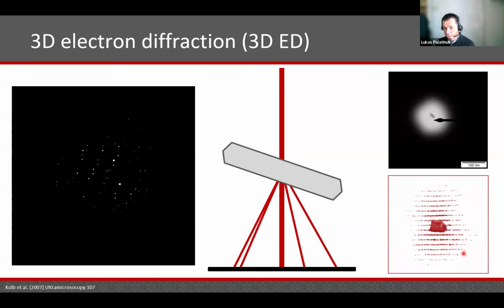There are certain experimental challenges that need to be overcome related to the stability of the crystal. You can imagine that keeping a crystal that is 20 nanometers in size in the beam while rotating plus minus, say, 50 degrees is a challenge. But these are experimental difficulties that have been to a large extent overcome in the past years. So now we can say that a reliable and quite robust data collection protocol is available, and we are able to collect this kind of data essentially routinely.